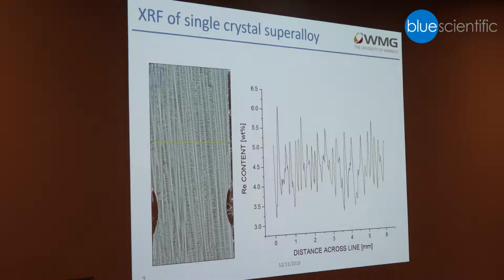This data is statistically good, so we can see that the variation in rhenium content varies between 3.5 to 5.5 weight%. And what this can do is it can allow us to target specific regions in a sample in more detail. So if we're going to do focused ion beam or SEM, it's very important to understand the bulk chemical distribution before we start looking at local areas.